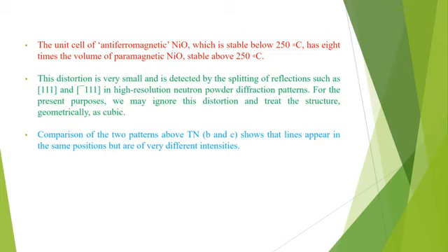The structure also shows a slight rhombohedral distortion involving a contraction in the 111 direction perpendicular to the planes of ordered nickel 2+ ions.